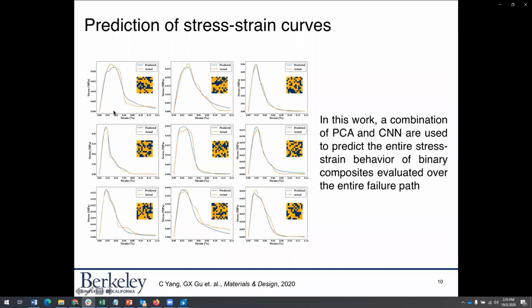And so here are two curves. This is a stress-strain curve for different unit cells. Again, the different colors represent different materials. And the two curves shown here are predicted from our models and the actual. And you can see that there's quite a good correlation between the two.